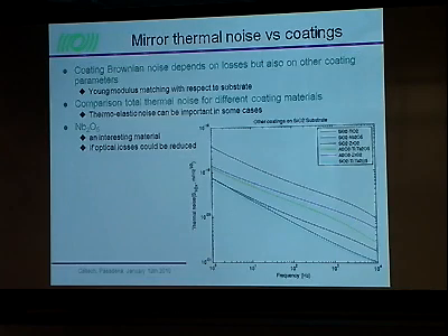The thermal noise actually depends on several parameters. So there is research which is ongoing at LMA to have a full repository of parameters for the different materials which can be used. And this plot shows the mirror thermal noise for different coating materials. In some cases, thermoelastic noise becomes important. In the case of titanium doped tantalum, the Brownian noise is the main limitation. This plot shows, probably you cannot see, that titanium doped tantalum is the best solution, but also that niobium pentoxide is very near in terms of thermal noise to titanium doped tantalum. So it's a material which we think is interesting, on which we hope we will have the time to work more.